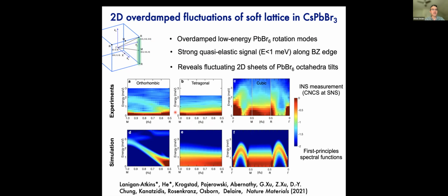Okay, but the thing that's really peculiar is that in a lot of oxide perovskites, you may see soft modes at high symmetry points like the R point or M point. In these materials, and I'll show you this is happening in the whole family of halide perovskites, you see this kind of overdamped quasi-elastic response at a continuum of wave vectors all the way between M and R, so that means along all the edges of the cubic Brillouin zone. And so it's really a kind of liquid-like type of dynamics for these wave vectors. So you've got these fluctuating two-dimensional sheets of lead-bromine octahedral rotations in real space, and this overdamped liquid-like behavior.